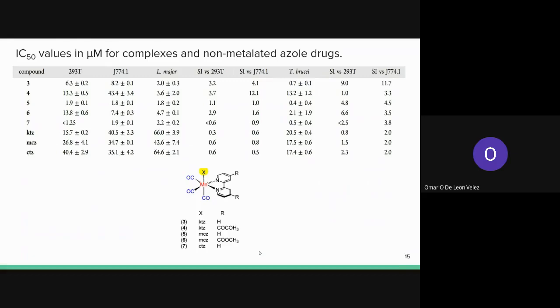So first, for L. major, they found that the metal complexes, which are in the third column, all did much better. They were more potent by a magnitude of 1 than their non-metallated versions, which is good, except for the fact that when they calculated the selectivity index, the selectivity indexes were considerably low, meaning that they were also damaging the mammalian cell lines. So based on these results, the authors established that these compounds are not suitable for anti-leishmanial chemotherapy, at least as they are.